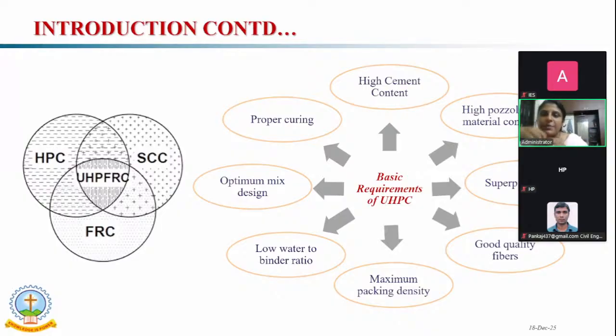In the case of normal conventional concrete, when you try to achieve high strength like above 120 MPa, the material will behave in a brittle nature. To avoid that, you have to consider fibers in order to change the character from brittle to ductile nature. We have incorporated good quality fibers. Then to achieve very excellent performance, we have considered the maximum packing density, that means minimum pores. The normal conventional mixing procedure or mix design cannot be appropriate for the development of UHPC. So we have considered some optimum mix design.